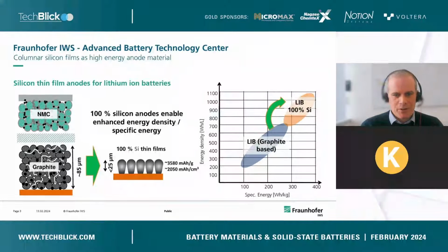We are especially interested in silicon thin films, which contain no other components than silicon, so 100% silicon, we call it. These are columnar films directly deposited on copper substrates, on current collectors. And with this, we can utilize the full capacity of the silicon. And with this, we obtain much higher specific capacity, both in terms of volumetric but also gravimetric capacity when compared to graphite. And this boosts energy density, gravimetric and volumetric on cell level when compared to lithium-ion batteries.